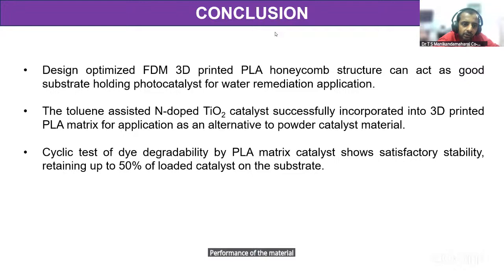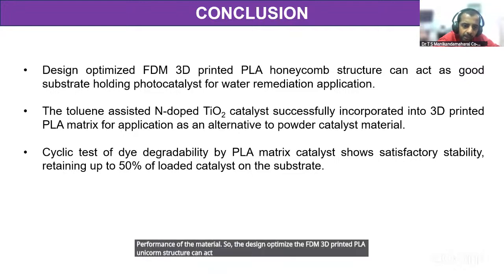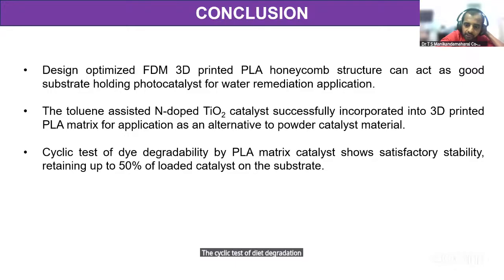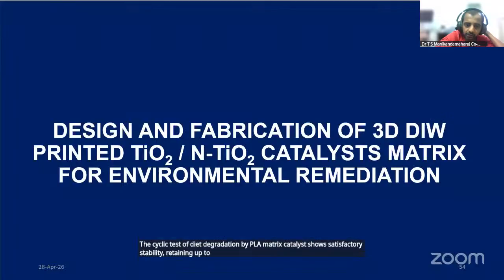The design-optimized FDM 3D printed PLA honeycomb structure can act as a good substrate holding photocatalyst for water remediation application. The toluene-assisted N-doped TiO2 catalyst was successfully incorporated into the 3D printed PLA matrix for application as an alternative to powder catalyst material. The cyclic test of dye degradation by the PLA matrix catalyst shows satisfactory stability, retaining up to 50% of the loaded catalyst on the material.